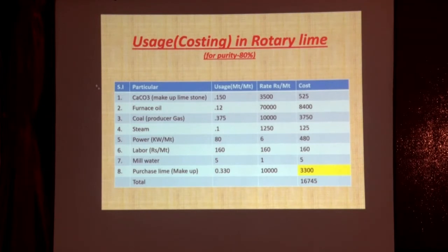This is the usage of the lime produced in the rotary lime kiln. Typically, data may vary slightly. The usual limestone makeup is 0.15, that is 150 kg per ton of CaO. Furnace oil is 120 kg. Some mills have achieved a bit lower, but with the addition of some other fuel, like coal along with the furnace oil. So the ultimate cost, if you reduce this makeup, because some mills are adding purchased lime also as a makeup, overall costing is very, very high in the rotary lime kiln.